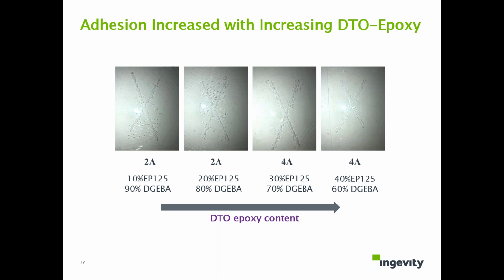So now let's look at how many percent DTO epoxy in the formulation gives improvement in adhesion on glass substrate. We added 10%, 20%, 30%, 40% DTO epoxy into bisphenol epoxy, and then made the same test. You can see that with 10% DTO epoxy in the formulation, you can start seeing improvement in adhesion from 0A control to 2A. When you increase DTO epoxy to 30% in the formulation, you can see significantly improved adhesion from 0A to 4A.